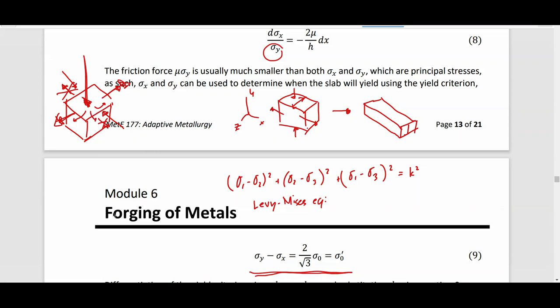Okay? So what counteracts that is, kung close die to, and imagine clay ulit, no? So para ma-counteract nyo, pwede nyong lagyan ng harang dito. So kunwari, kung may harang kayo dyan, then if you squash this clay, kahit gusto niya mag-flow outside papunta sa direction na to, kina-counteract siya by the reaction ng wall or harang na nilagay nyo. Tama? So ang only direction na mapupunta niya is actually this one and this one.